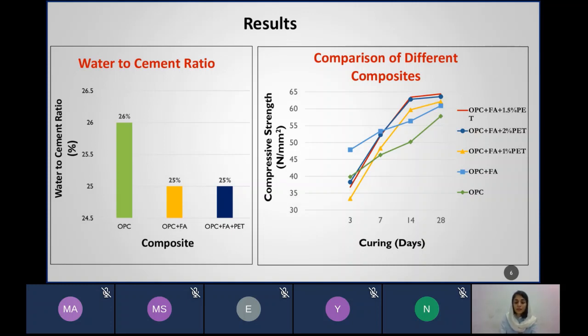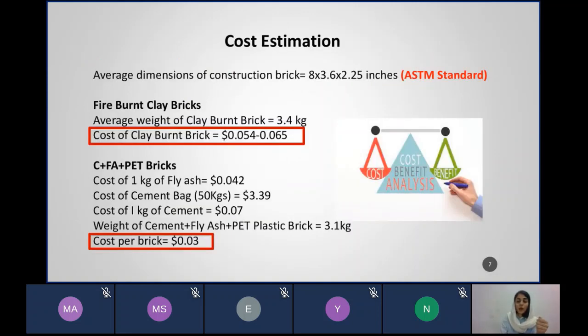Now here comes what percentage of plastic can be added. As I performed my research, I found out that you can add plastic as a partial replacement of cement by 1.5%, because when I added 2% of plastic, the composite became brittle and more prone to cracks. So you can add 1.5% of plastic with fly ash and cement to make a construction material that has the highest compressive strength among these.